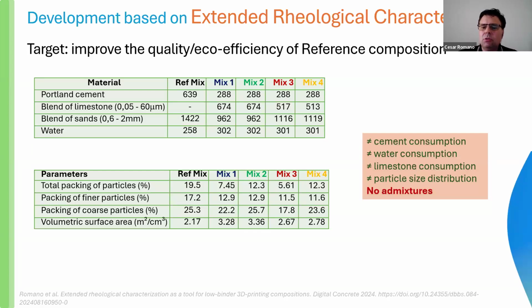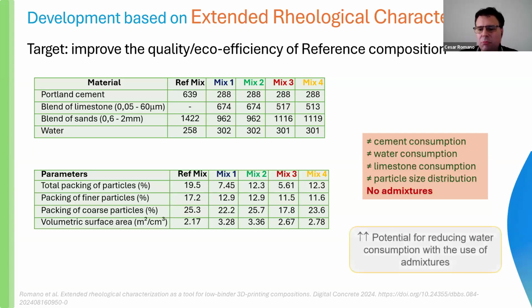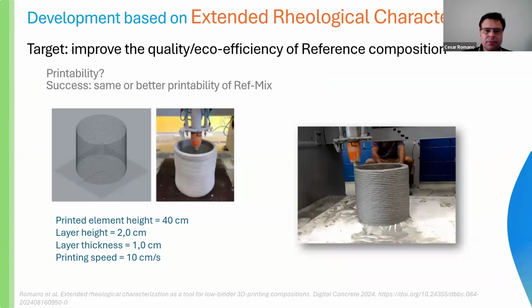We used limestone. We had different particle size distribution. We didn't use admixture because the guys from the machine said to us that they didn't use admixture. So we have potential for reducing water consumption with the use of admixture. We can have better properties if we reduce the amount of water using admixtures, for example, and the printability also.